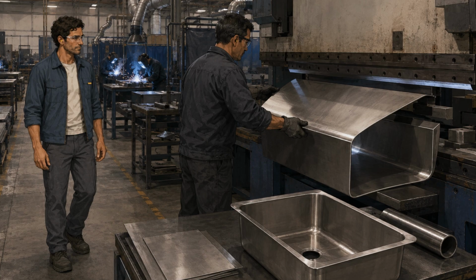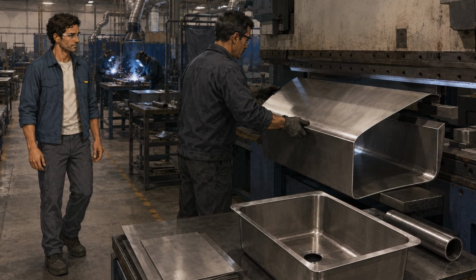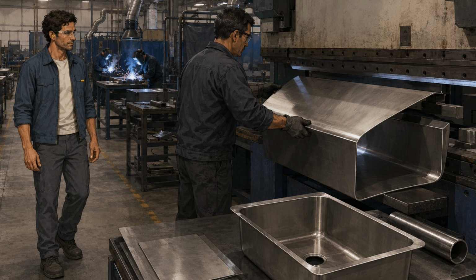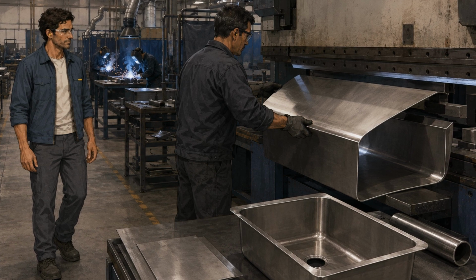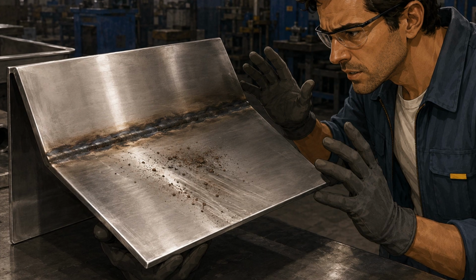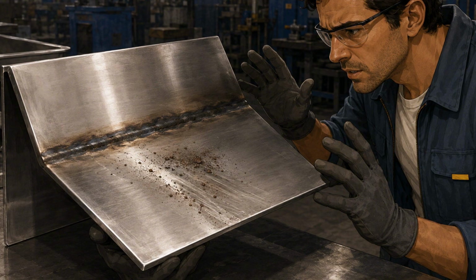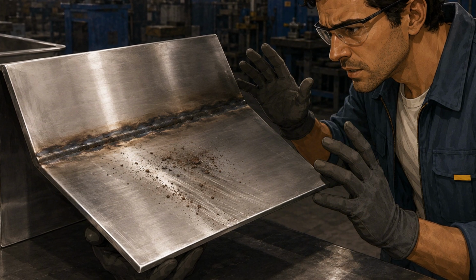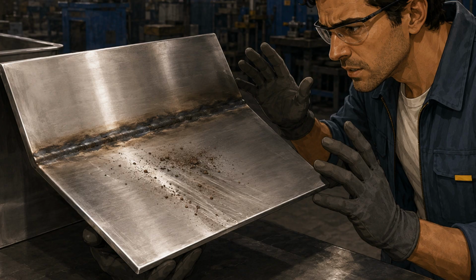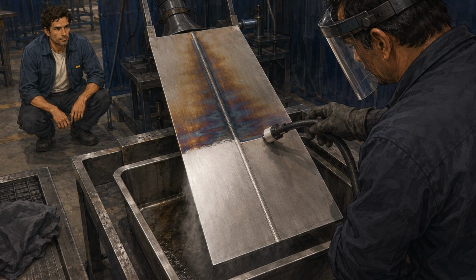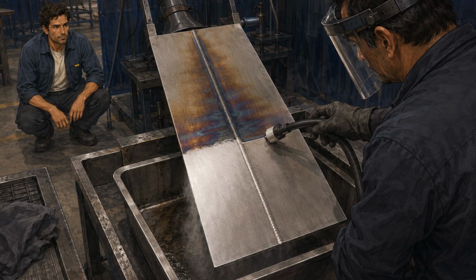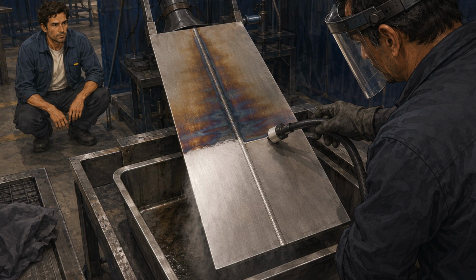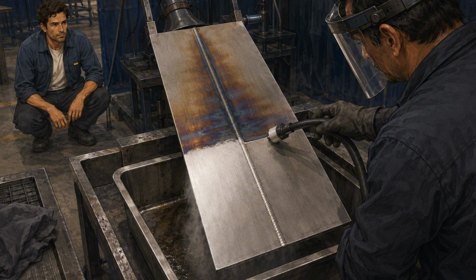The material then enters another workshop. A fabricator cuts, bends, draws, machines, and welds it into sinks, tanks, tubes, instruments, cladding, or valves. Every operation can preserve or damage future performance. Dirty tooling can press ordinary iron into the surface. Excessive grinding can create rough retention sites. Poor shielding can leave heavy oxide around a weld. Heat tint beside a stainless weld is more than a color. It marks a region altered by high temperature. Correct cleaning can remove affected surface layers and support a sound passive condition.